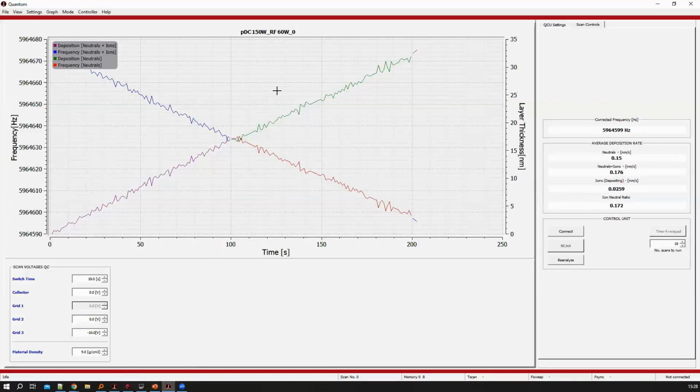So the idea is, these don't have the default values actually, but you would measure the ion energy distribution function, and let's say your highest energy ion is 30 eV because it's just the plasma potential. So you'd put in here something like 60 volts to block all those ions. You would have a secondary electron repeller, which would be, I don't know, some negative value with respect to this.